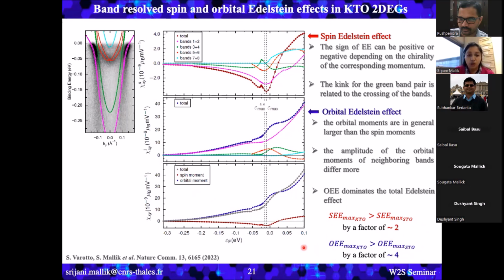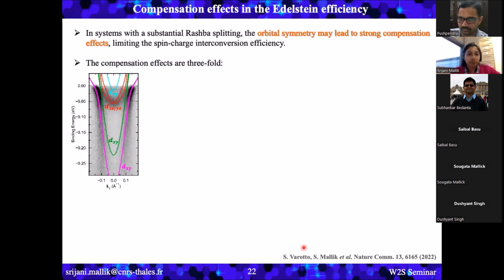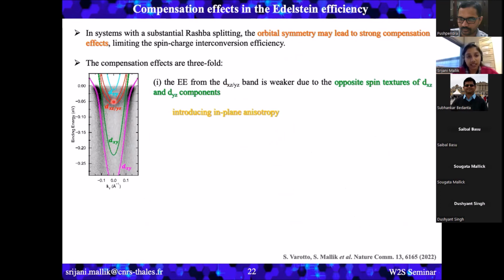So I would like to give a brief summary of this part, because from these theoretical calculations, we saw that although our system shows very large Rashba spin orbit coupling, still there are some compensation effects playing a very important role in the spin charge interconversion efficiency. So the compensation effects are mostly threefold. The first one is the Edelstein effect coming from the dxz, dyz. So this band pair is weaker due to the opposite spin texture of the dxz and dyz components.